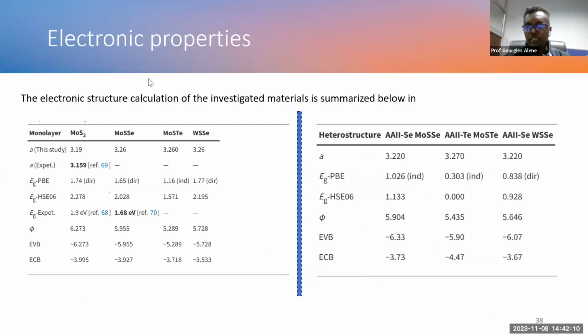One thing I have to mention here, when we calculate the HSE band gap value for AAII-Te MoSTe, it is zero. This means it is a metallic system. If it is metal, then it is not obviously good for photocatalytic water splitting application. So what we have done is we excluded this material from further investigation in our study.